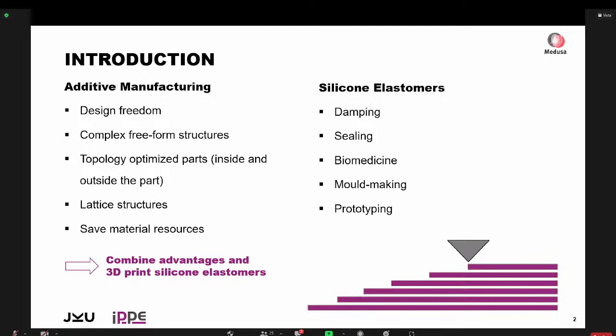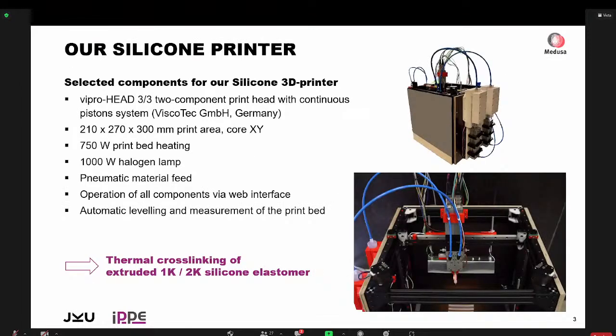The ones from additive manufacturing, you probably all know. But silicone elastomers have very good damping properties. They're used for sealing in biomedicine. And usually they're processed by mold making or prototyping also, and for these applications. And now we wanted to combine those advantages. So what we did is we built a silicone 3D printer. We used a commercially available print head, the vipro-HEAD 3/3 from the company ViscoTec, which is allowing us to print with 2 component silicones that are going through a static mixer and then are extruded through a nozzle that we can choose in size.